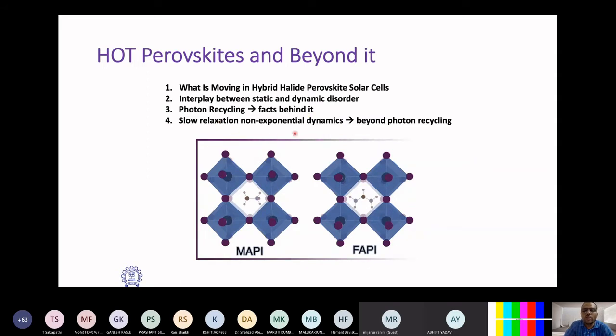Slow relaxation, non-exponential decay time. How do we understand this? Whether these are the things which are observed in gallium arsenide as well, and the results which they use to say that this is photon recycling. But we can explain this slow relaxation, with non-exponential dynamics, beyond the photon recycling kind of physics concept. That's what we showed, and some other research groups around the globe have shown.